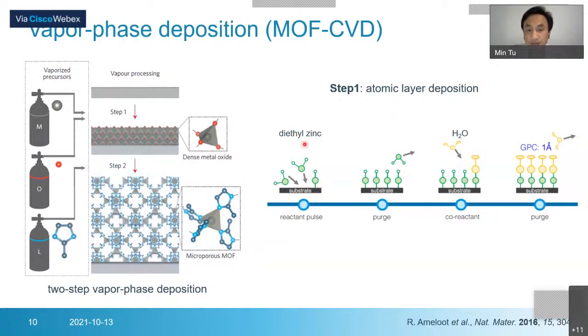First you have diethyl zinc deposited on the surface. Then you have a purge cycle to remove unreacted precursor. Then you have water to react with diethyl zinc to get ethane out. By repeating this procedure many times, you can have different thicknesses of zinc oxide. The growth per cycle is 1 angstrom, so this method can tune the thickness very precisely at the angstrom level.